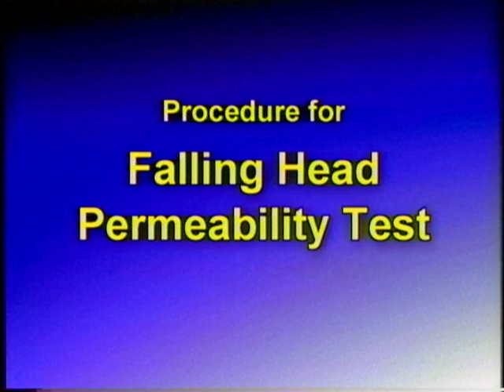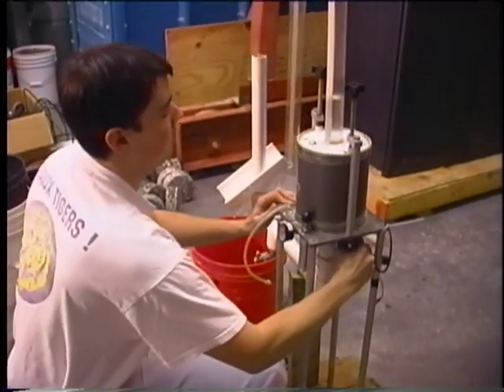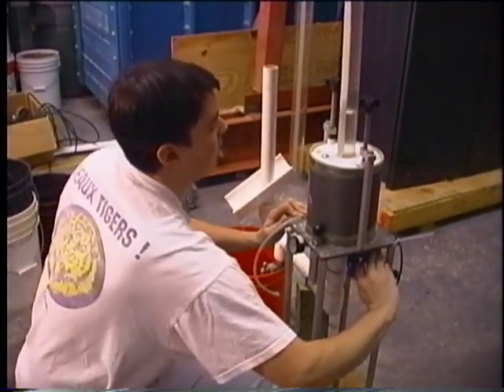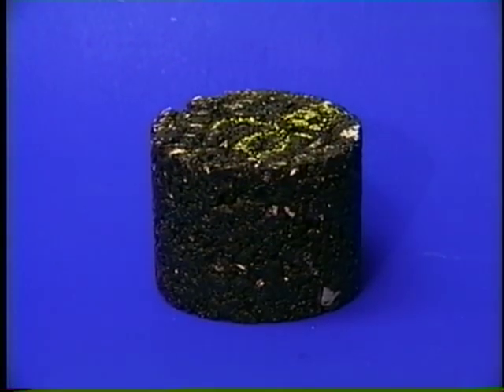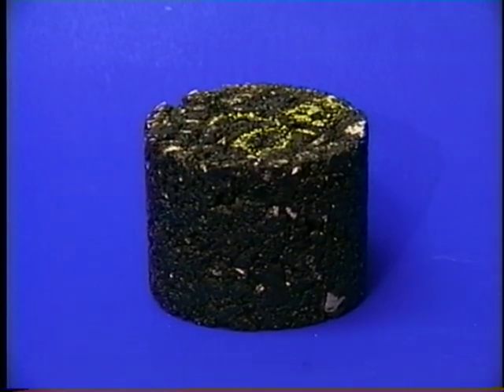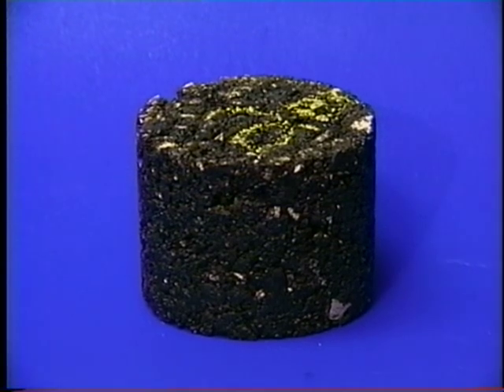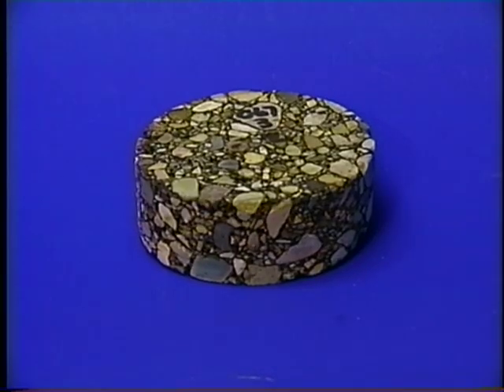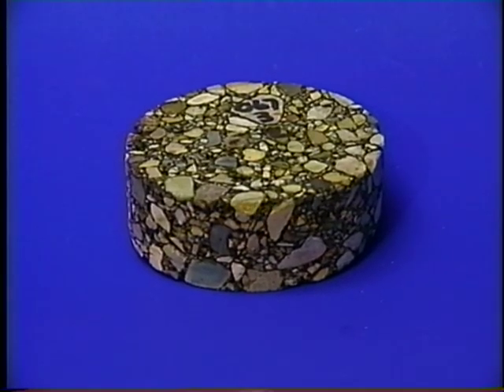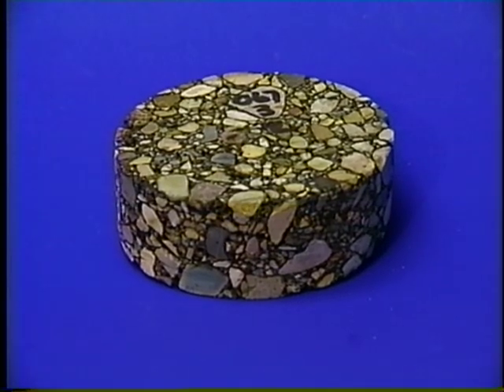Procedure for falling head permeability test. The permeability test that we will use determines the flow rate of water through hot mix asphalt, or HMA, mixtures. The test is conducted using 6-inch samples of compacted HMA or cores of HMA taken from the field. Field cores must be separated into each lift.